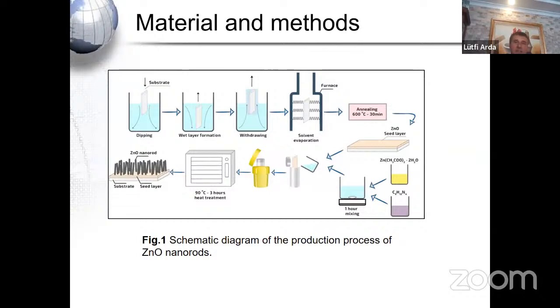Materials and methods. I told you that we use a hydrothermal route. That means zinc oxide nanorods were fabricated by using this method. All chemicals used in the experiment were taken from Sigma Aldrich. Glass substrates were used for the growth of zinc oxide nanorod arrays. The fabrication process is shown in the figure. Two different zinc oxide nanorods were fabricated. One of them is just nanorods. The second one, we fabricated nanorods on the seed layers, and the seed layers were on the glass substrate.